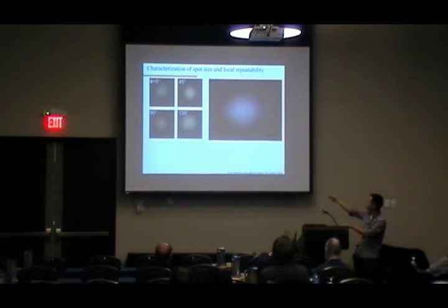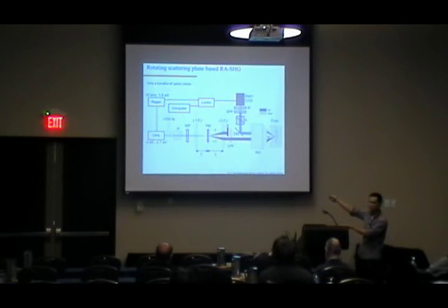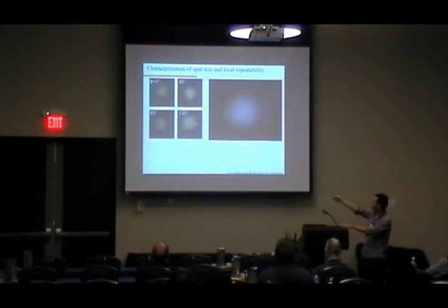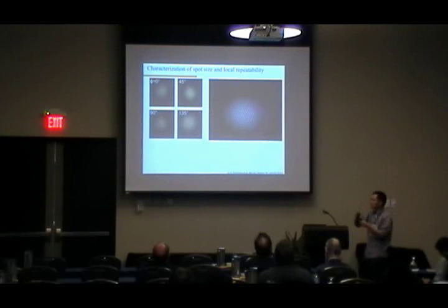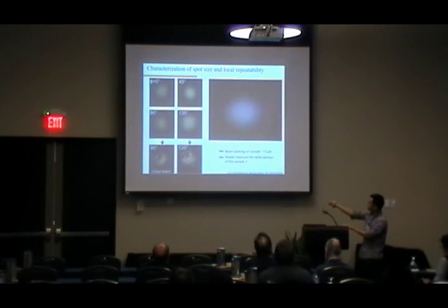Rather than letting one beam of light through, for alignment purposes, we remove this beam block and let both beams come through and converge on the sample, thus forming what's called an optical grating. This optical grating acts as a ruler for us. You can see how the grating evolves as the scattering plane rotates. Using this optical ruler, we can tell how far we've moved as we rotate the scattering plane. We can find some marker on the sample, let's say a defect, and quantify how much our beam moves around on the sample. In our case, we can get things to better than about a micron.